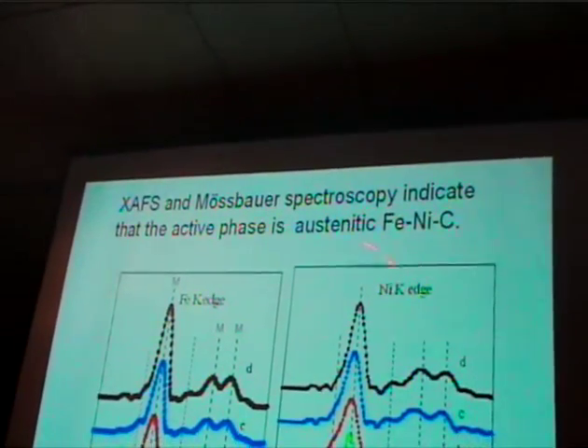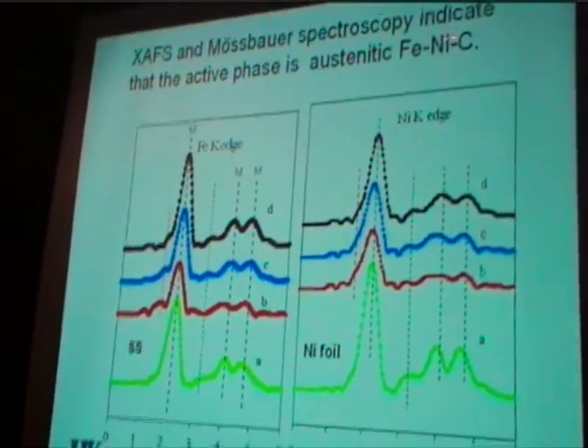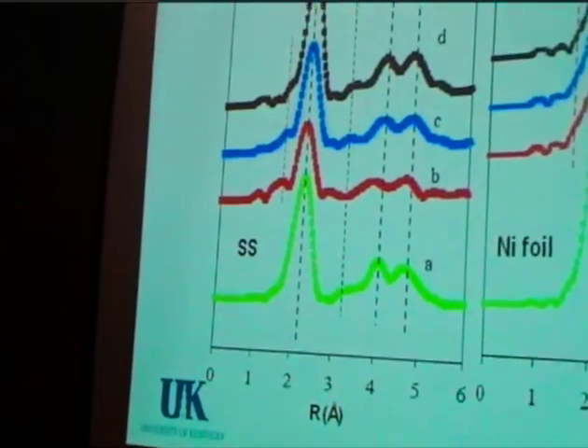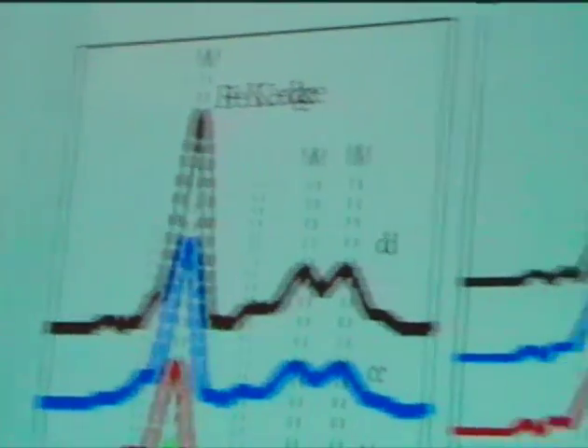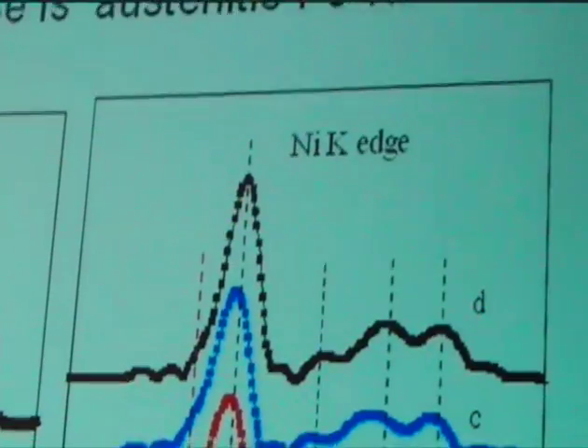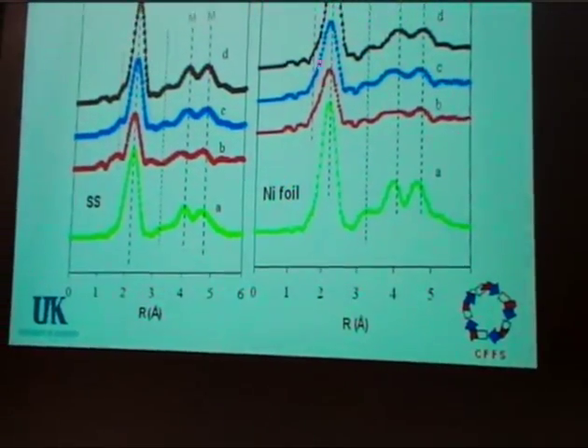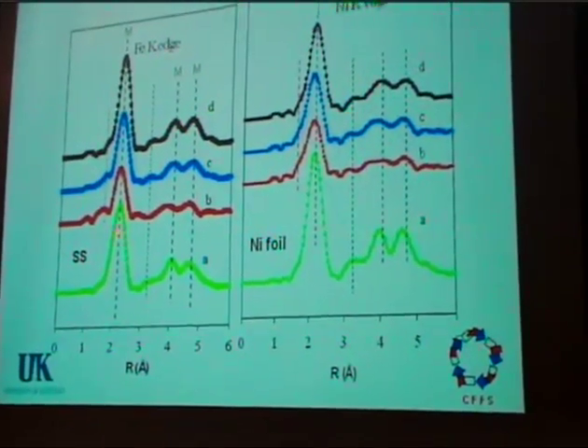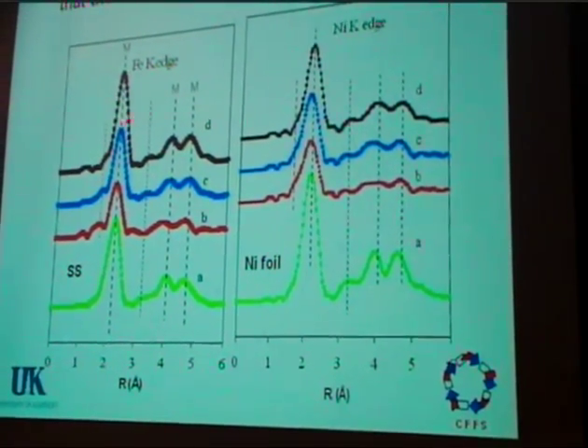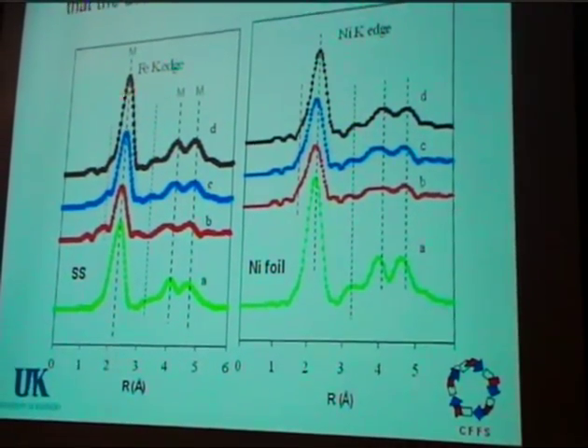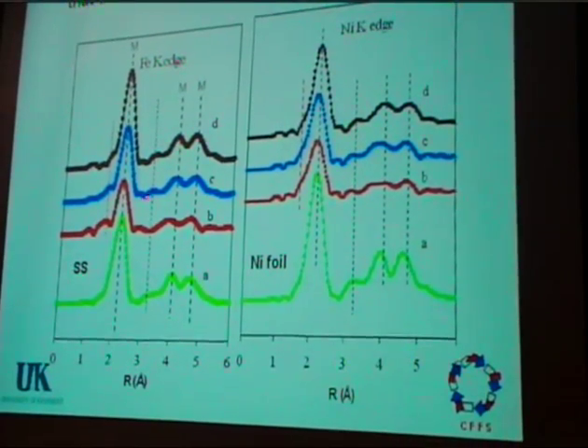Again, we like to use Mossbauer and EXAFS to indicate what the phases are, and indeed the primary active phase still appears to be the austenitic iron nickel carbon, and you can see this really from the positions of the near neighbor shell peaks in these radial distribution functions that are produced from the XAFS spectra.